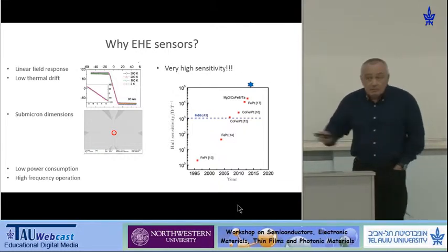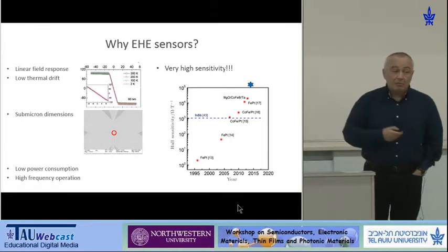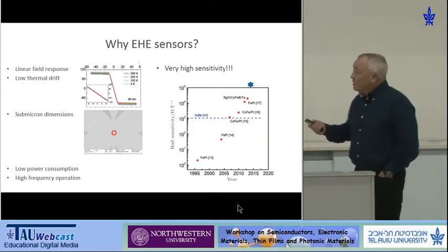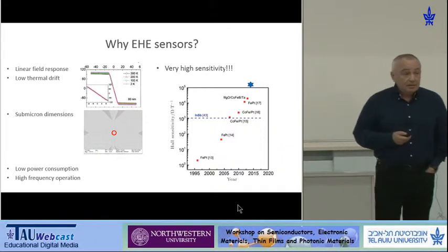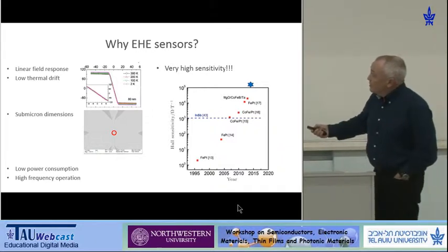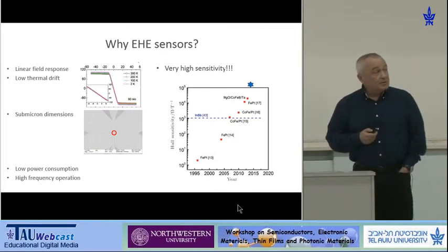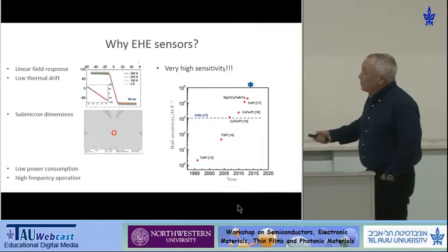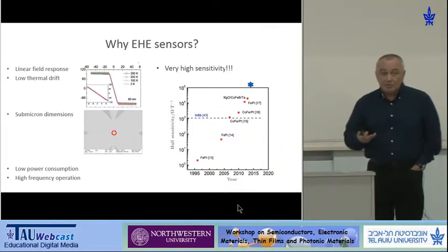I mean, conductance, Hall effect and the number of carriers in a semiconductor depend strongly on temperature. Here, we are able to tailor the material in such a way that the slope will not be dependent on temperature. It is also small, which is fine, with low power dissipation because of high resistivity, but probably the most important is